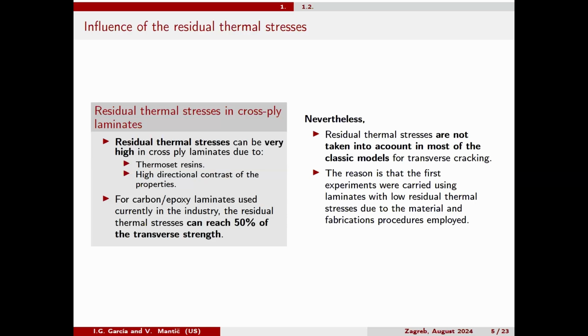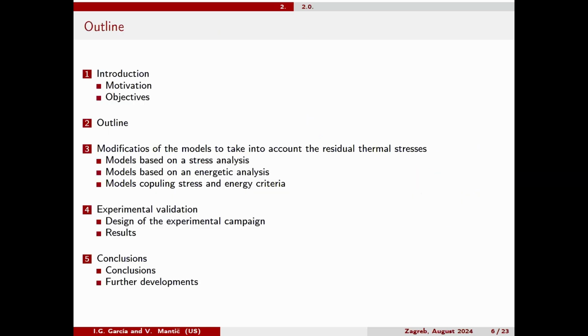Why are they not, up to now, in these theories? The reason, I guess, is that the first experiments that, for example, García and other co-workers did, they did in glass epoxy, where the contrast between the directional properties of the coefficient of thermal expansion is much lower than in carbon epoxy. And in addition, the fabrication procedure wasn't the typical autoclave curing and so on. So they didn't expect actually great residual thermal stresses. So this is the outline of how we are going to try to do that.